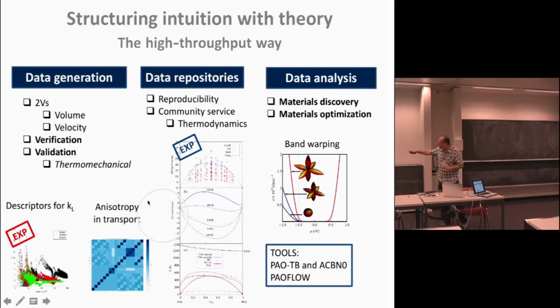The first one is that we discovered descriptors that were actually good to predict the thermal conductivity without ever computing the thermal conductivity. And this was verified experimentally. Then, exploring little databases, we learned a principle of anisotropy that turned out to be very interesting and brought us to explore criteria to induce or remove anisotropy in transport coefficients, and also ways to actually compute properties that are optimizing the conductivity. This is band warping.